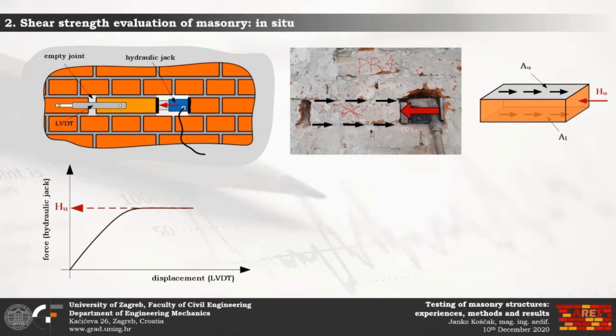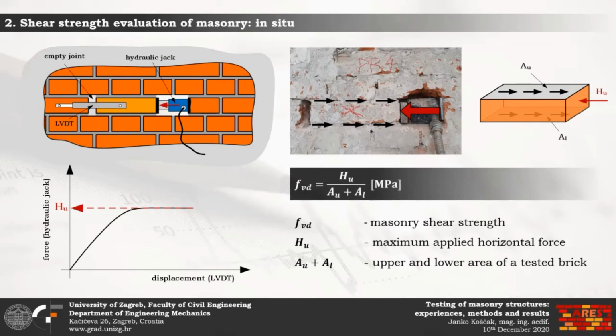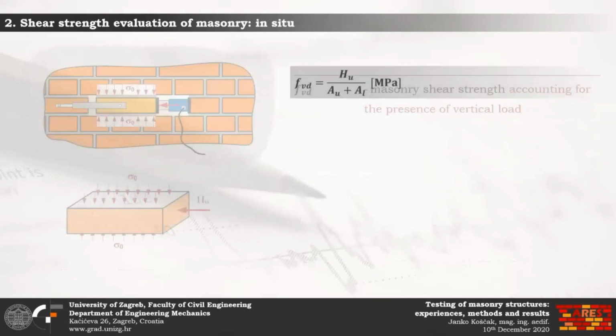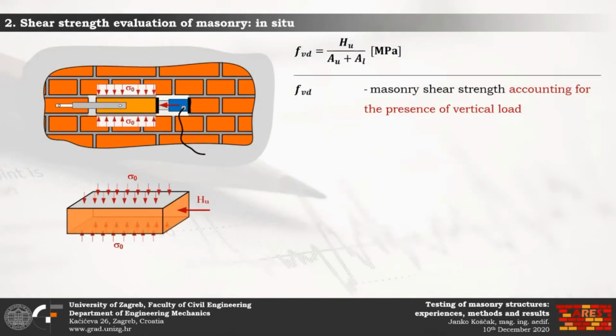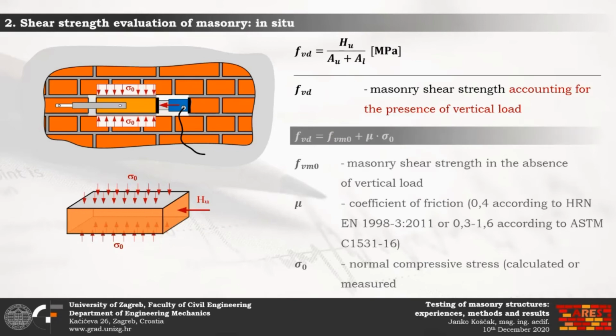Of course, the masonry shear strength, f_vd in this expression, can now be calculated by dividing the maximum applied horizontal force measured, this is H_u, by the sum of the upper and lower area of the tested brick. It's important to note that the value of shear strength measured with this simple test takes into account the presence of the vertical load. Of course, because of the existing vertical force within a tested wall, some normal compressive stress is acting on the tested brick, and in combination with the friction coefficient, it increases the value of the masonry shear strength. This can be seen from the expression.